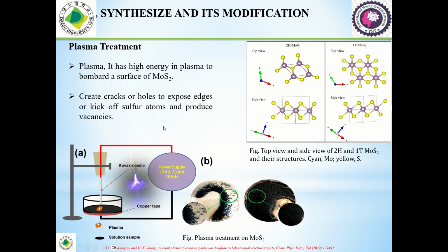We can clearly see in this figure plasma treatment, which has high energy to bombard the surface of MoS2, and which cracks it and makes holes to expose edges or kick off the sulfur atoms and produce sulfur vacancies in MoS2. It can enhance the conductivity, wettability, and hydrophilicity, and this technique can also change the phase structure of the MoS2, from the 2H phase to the 1T phase, which is from semiconducting behavior to metallic behavior.